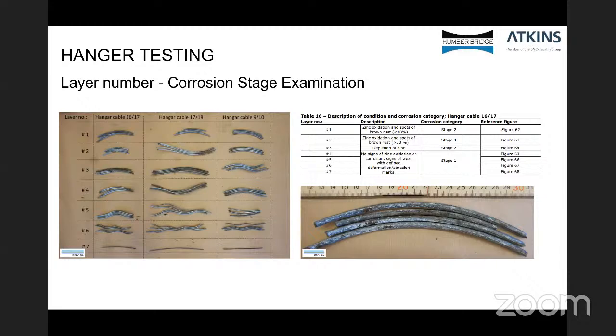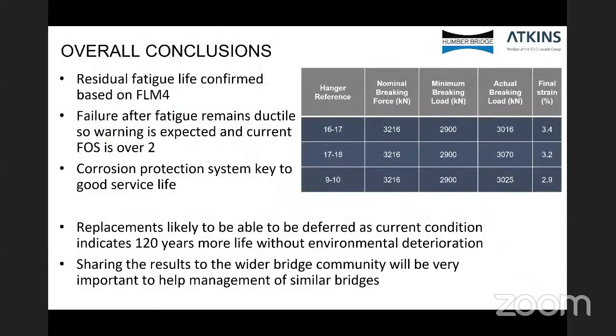If you can go to the next slide, please. Okay, so overall conclusions then. There's a residual fatigue life confirmed based on the FLM4. The fatigue testing proved that the hangers had significant further life. Failure after fatigue remains ductile, so warning is expected, and the current factor of safety is over 2. The corrosion protection system is key to good service life. Replacement is likely to be able to be deferred as current condition indicates 120 years more life without environmental deterioration.